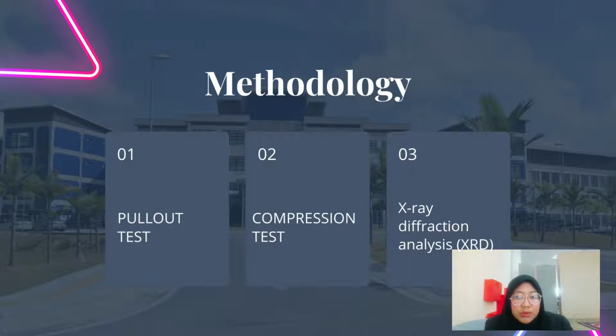Alright, for the methodology, we have three tests that will be done. First, pull-out test, compression test, and X-ray diffraction analysis, known as XRD. For the methodology flowchart, first I identify the problem. Then I find the literature review that's suitable for the problem, and start to prepare the material. The materials that I use in this methodology are ordinary Portland cement, grade 25, fine aggregate and coarse aggregate, POFA and EPS. And then start to prepare the samples. Between the prepared samples, there are two types: concrete mixed with 30% POFA and EPS, and concrete mixed with 0% POFA and EPS.